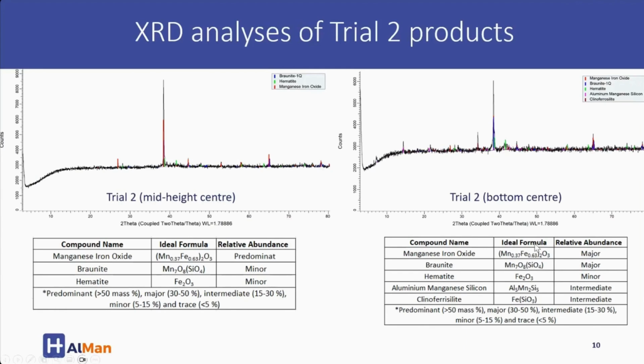The reasonable explanation for this is that the time allowed for pre-reduction was not adequate to ensure all these oxides are converted to MnO. This work also confirmed or validated the preliminary modeling work done by one of the partners in the consortium.